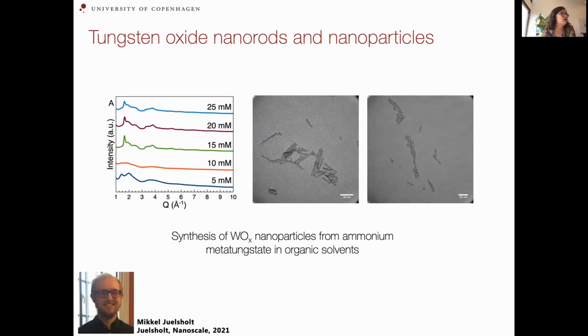for crystalline materials. So we wanted to investigate these, and my former PhD student, Mikkel, went to the lab and developed a synthesis where we could, super simple, take ammonium metatungstate in some different organic solvents, and by changing the concentration of the ammonium metatungstate, he could get different kinds of particles out. So these up here, we'll talk about first. They have these characteristic somewhat Bragg-like peaks, and then down here when we have lower concentration, it's just these broad features. And here's some TEM images of, I think, this sample here. So we can make these nanorods, which we wanted to investigate.